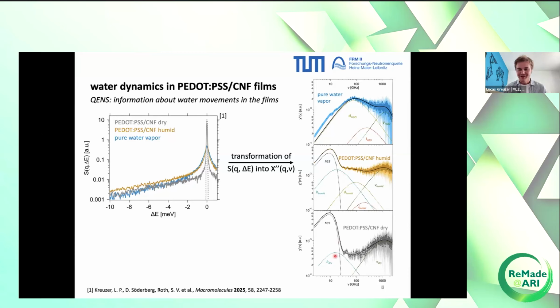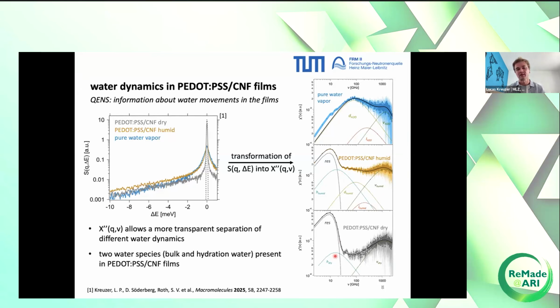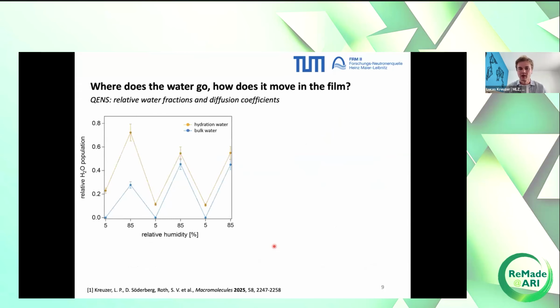So very complicated slide with a lot of information, but if you take away two points, I'm already happy. So the first one would be this transformation to the susceptibility allows you a very transparent separation of the different water dynamics. And we have two water species present, bulk and hydration water. And now we can take these two water species and plot the ratio of these as a function of the relative humidity. And this is what I've done here. So here you see the relative water population, hydration and bulk water, as a function of relative humidity.